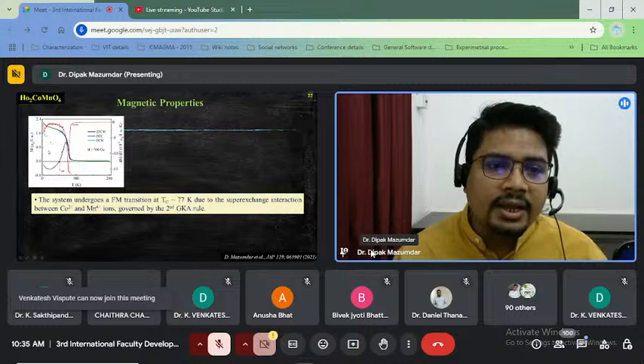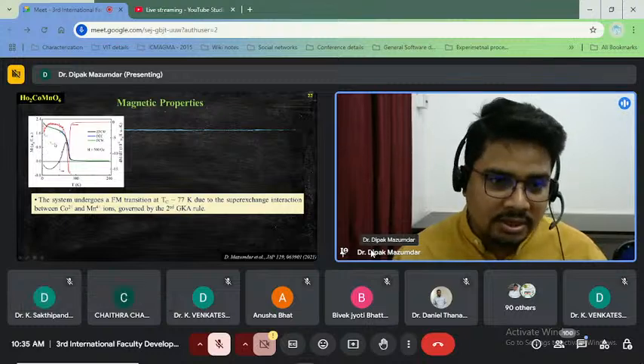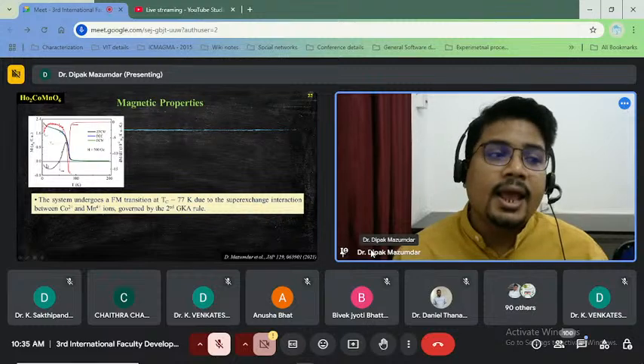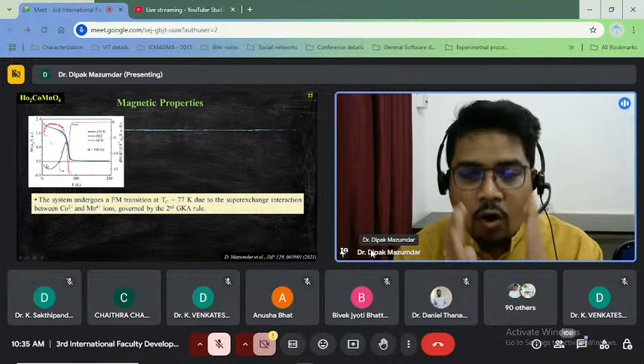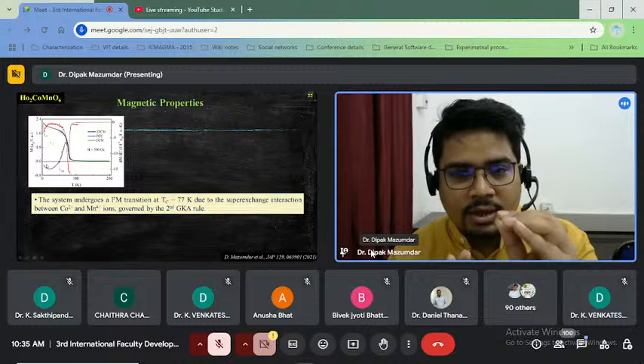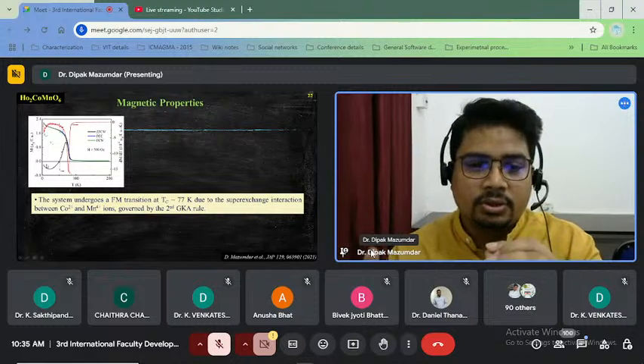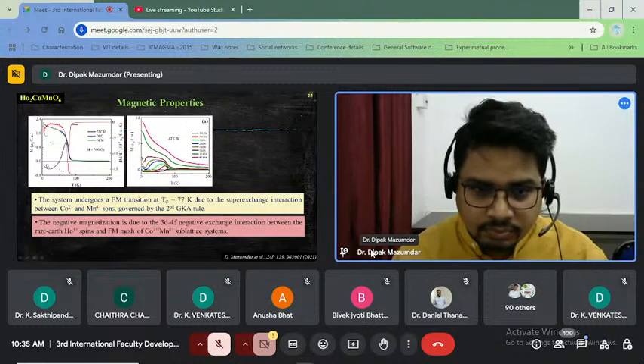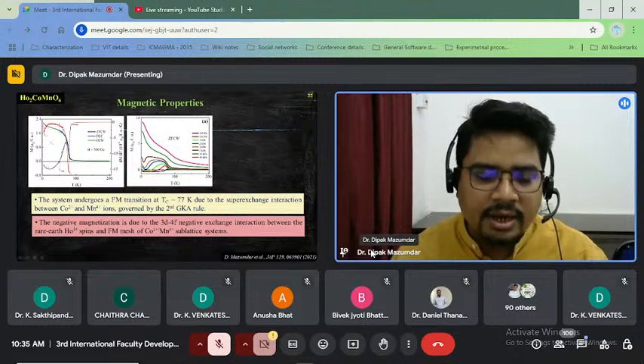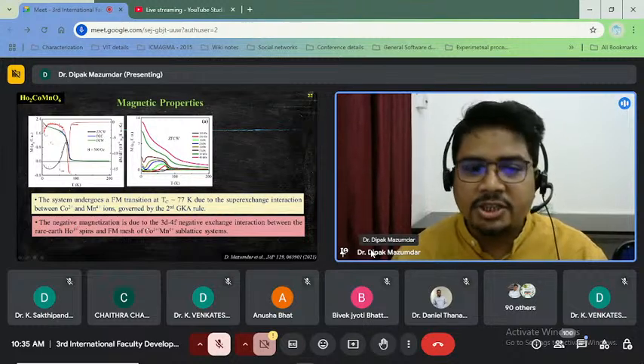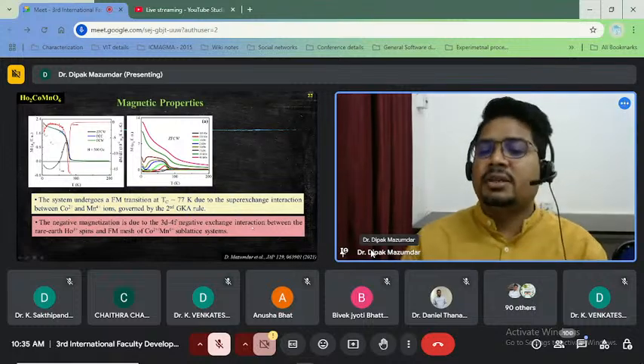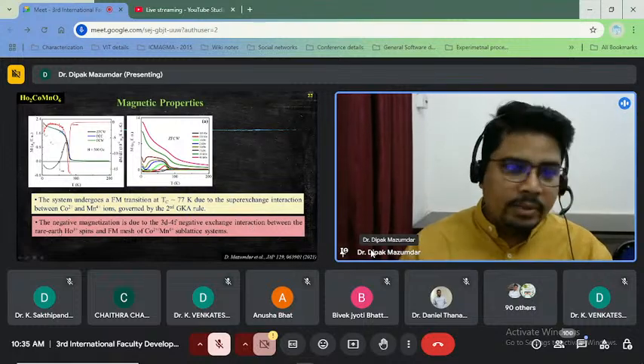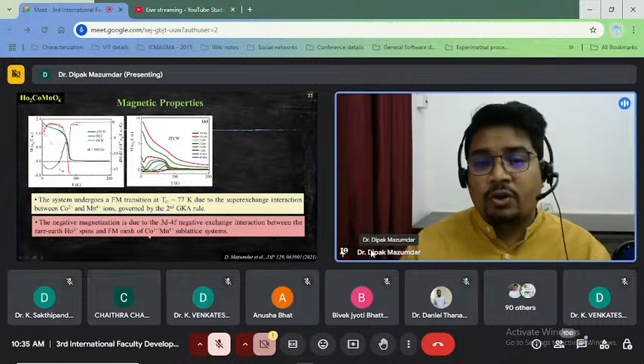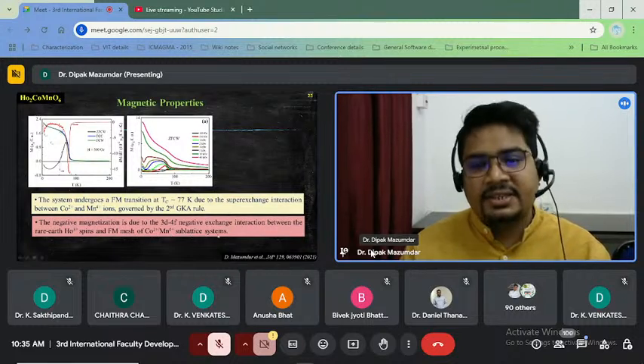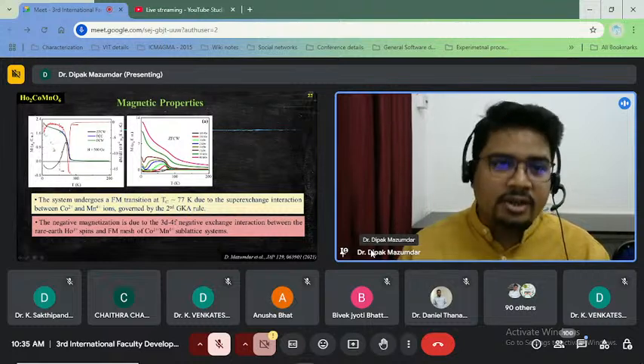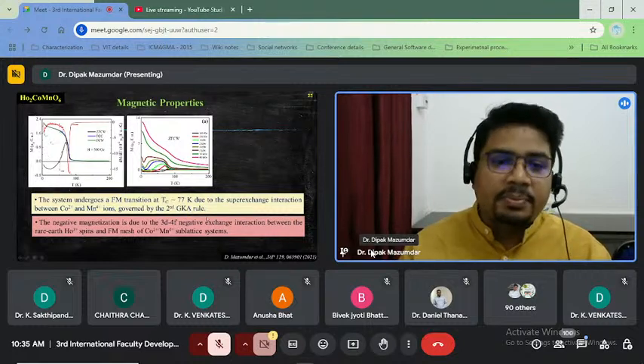And you can see a negative exchange interaction, and this comes from the anti-parallel alignment of cobalt, manganese ions and holmium ions. You can see here I have written that the negative magnetization is due to the 3d-4f negative exchange interaction between the rare earth holmium spins and the ferromagnetic mesh of cobalt and manganese in this two-sublattice system. And details of this negative magnetization are already discussed in my paper.